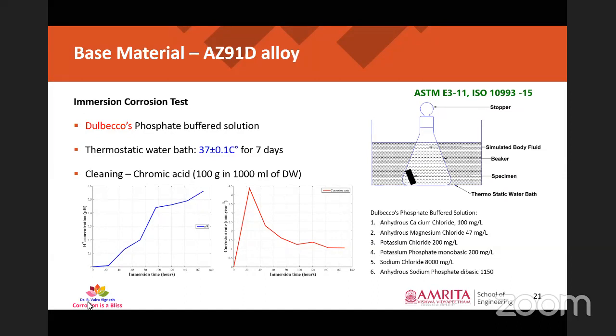Initially, the corrosion rate of the material increased to 4.37 mm per year after the first day of corrosion. With increase in immersion time, the corrosion rate stabilized at around 1.05 mm per year after 144 hours of immersion, that is after the 6th day. So we could generally see that the corrosion rate of the material is too high for biodegradable implants. So obviously we have to go for a process to engineer the corrosion rate. That is what we have concluded here.